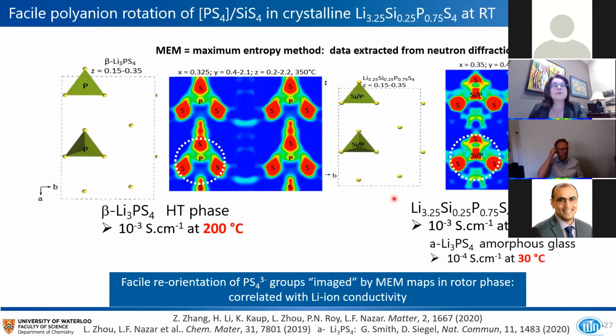This inspired us to try to stabilize this high temperature so-called beta phase at room temperature by incorporating extra lithium into the material. What this does is it expands the volume and it allows this rotor behavior to occur at room temperature. So you can see the same rotor behavior at 350 degrees versus the rotor behavior now at virtually room temperature. And the same rotational behavior is responsible for lithium conductivity in that amorphous glass I mentioned. This was proven by our colleague at Michigan, Don Siegel, who recently published on the glassy Li3PS4 phase. So this is exciting because simply by stuffing this structure with lithium, we expand the volume and turn on this polysulfide, thiophosphate rotational behavior.